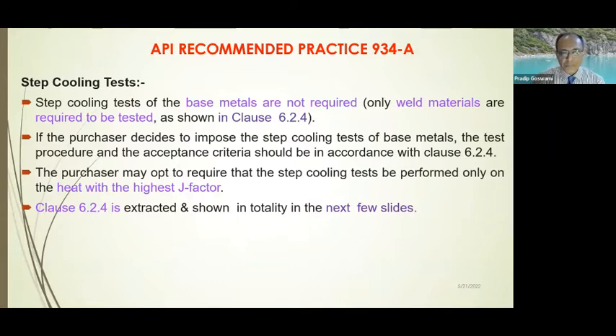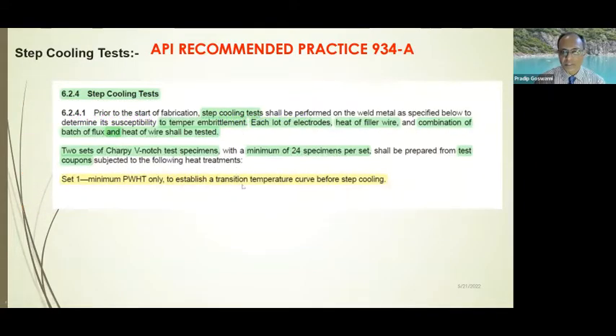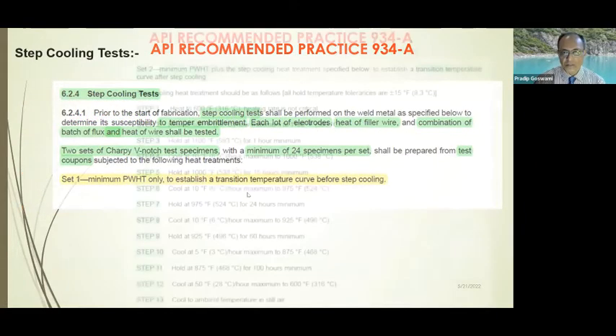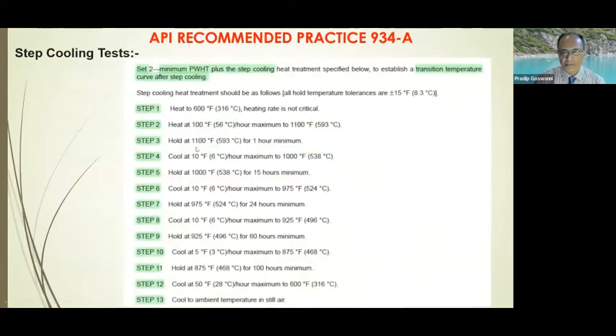While these steels undergo fabrication, there is a critical test called the step cooling test. The step cooling test is a fundamental test which detects the ability of the steel to withstand or resist temper embrittlement. As you can see here, the step cooling test is highlighted, and these are the various steps.